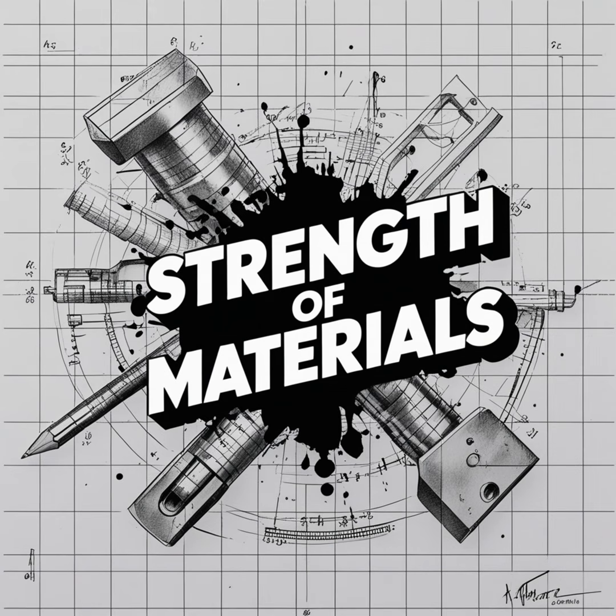Correct. It also provides intense cold working of the surface. Just as we discussed earlier with strain hardening, massive plastic deformation causes the dislocations in the metal to tangle up and lock together. So it's double protection. Yeah, this cold working significantly hardens and strengthens the surface layer, providing drastically better resistance against wear, intergranular corrosion, and it even physically hammers shut microscopic porosity in cast metal parts. It is just a brilliantly elegant engineering solution. Use brute force to induce a squeeze that stops cracks from breathing.